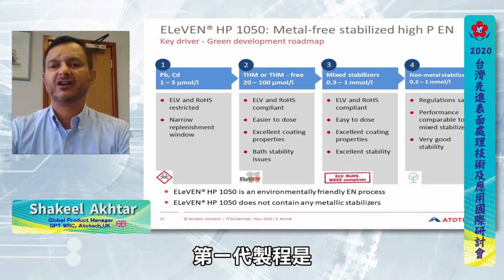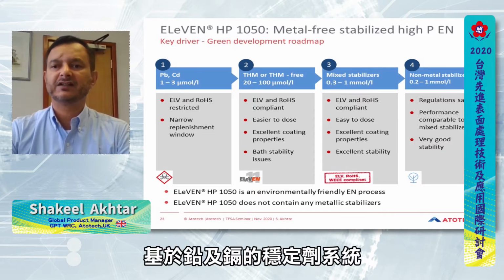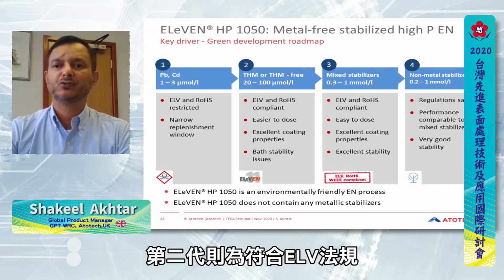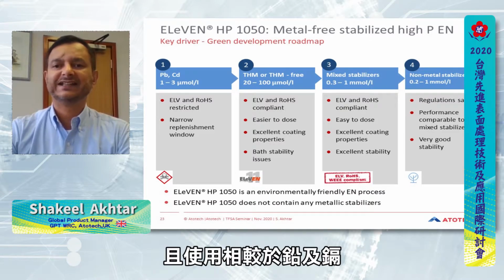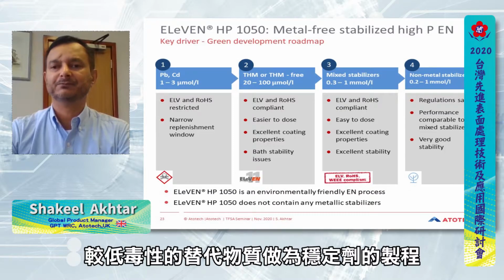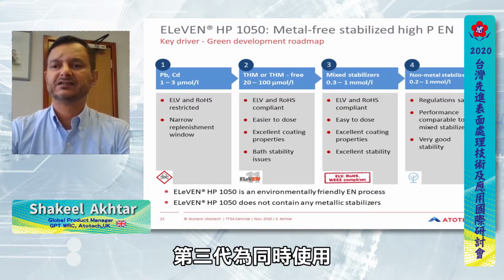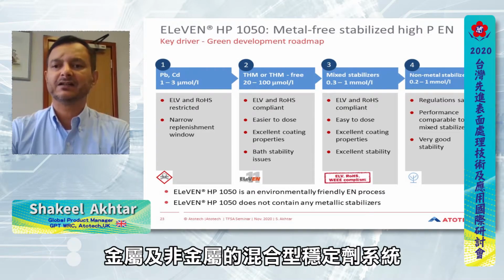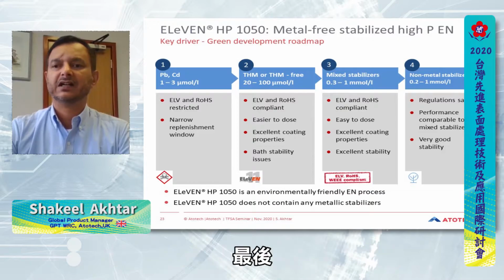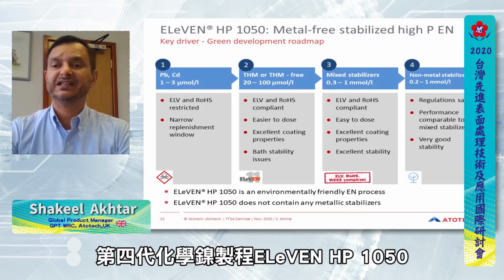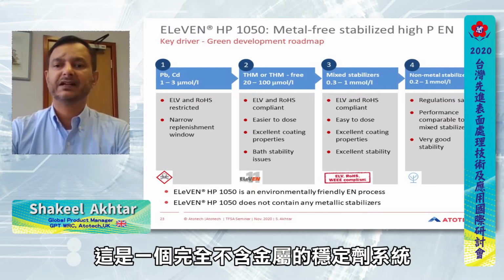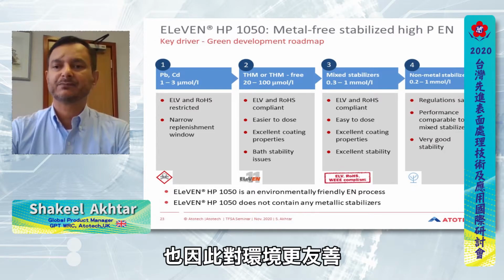The first generation of processes were based on lead and cadmium stabilizers. The second generation were developed to comply with the ELV legislation and used alternatives which were toxic but less than the lead and cadmium. The third generation were based on mixed stabilizer systems using both metal and non-metal stabilizer systems. And finally, we have the fourth generation, which is our ELeVEN HP 1050, and this is completely metal-free stabilized and thus better for the environment.